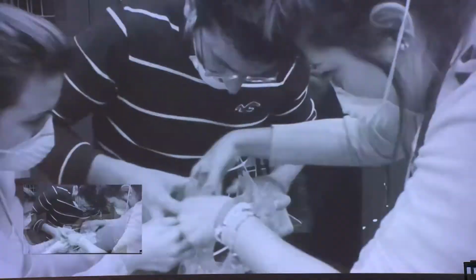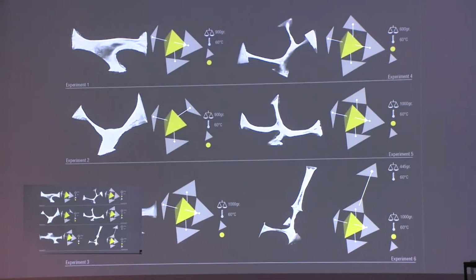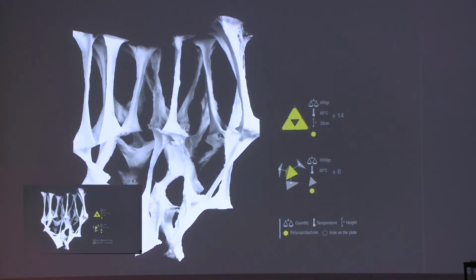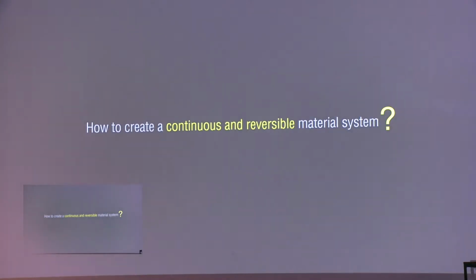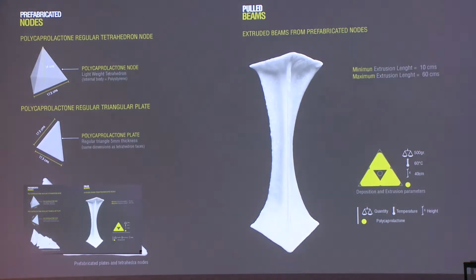And also trying to get material continuity, we tried to explode or kind of pull a tetrahedron node, which we couldn't control really well. And we also had the issue of the rigid acrylic plates, so we couldn't get the continuity so well. So how to create a continuous and reversible material system? We came up with prefabricated nodes. The first prefabricated node is a tetrahedron node that is made of polycaprolactone, is lightweight, a regular tetrahedron, and a polycaprolactone regular triangular plate, which has 5 millimeters thickness. And we are pulling beams from those nodes. The minimum extrusion length is 10 centimeters, and the maximum extrusion length is 60 centimeters.